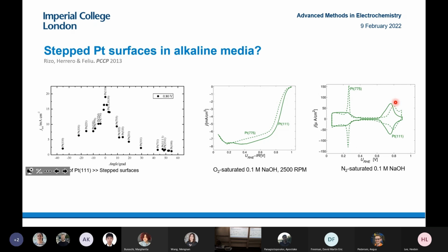We thought, okay, maybe what's the reason? So we actually looked at the CV like before. We found the CV in alkaline media also showed a destabilization of the OH peak on a step surface. So we didn't really understand it. If you're trying to make experimental volcanoes, this is what we'd expect from theory. But we see destabilization of OH, and yet we see lower activity than platinum-111. So it seems like the Sabatier volcano doesn't actually work in alkaline media. So this is quite interesting.